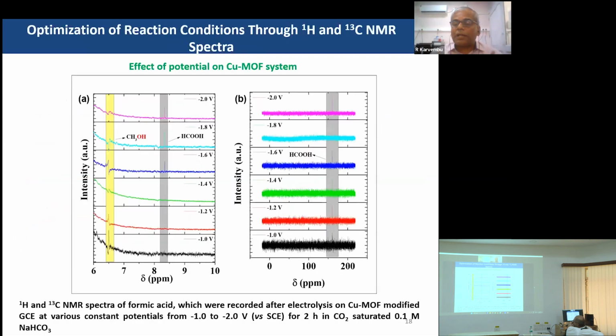We used proton NMR and carbon NMR techniques to analyze and quantify the product obtained from the reduction of carbon dioxide. From the H1 NMR spectra, we could identify the formation of formic acid, observing a chemical shift at 8.3 ppm. We could also observe a meager formation of methanol. From the C13 NMR, we again observed the formation of formic acid from the chemical shift value at 160 ppm. These are the spectra obtained when pristine copper MOF was used as an electrocatalyst.